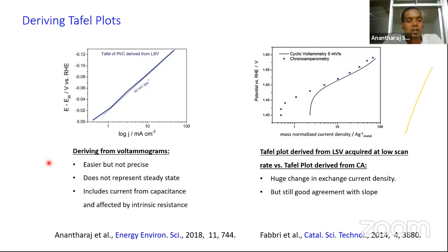When I explained the Butler-Volmer relationship, the current-potential relationship, I told that the current varies exponentially in the high overpotential region. That means if you plot the logarithm of the current against the overpotential, which is free from IR drop, you will have a linear line, the slope of which is equal to the constant in the Tafel equation, something between 30 to 120 millivolt per decade. Depending on this, you can also predict the number of electrons transferred in the rate determining step, and also the mechanism by which the reaction is occurring.